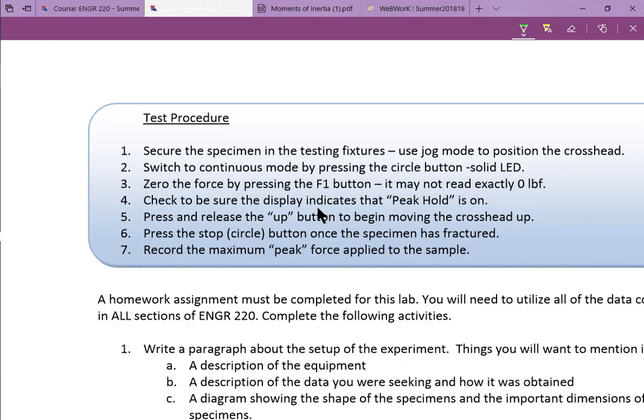Peak hold is important — it can be on or off, set in the menu. It should be on, but someone could have turned it off. If peak hold is not on, the force will go up, the thing will break, and it'll drop back to zero — you won't see the peak force unless you were watching at that exact moment. With peak hold on, the peak force experienced during the test stays on the screen so you can read it after fracture.